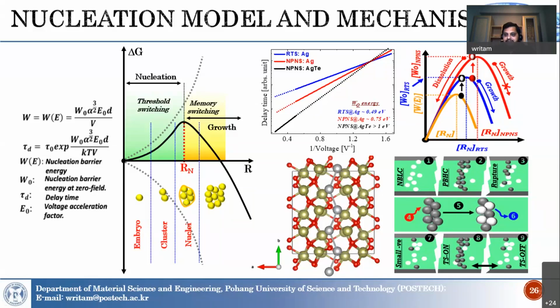After the rupture process, the complete filament will not definitely break entirely; it will break in some part, and that is how with a very small voltage we can achieve very stable switching, because we do not have many diffusions of silver in random locations. We have a very localized diffusion.